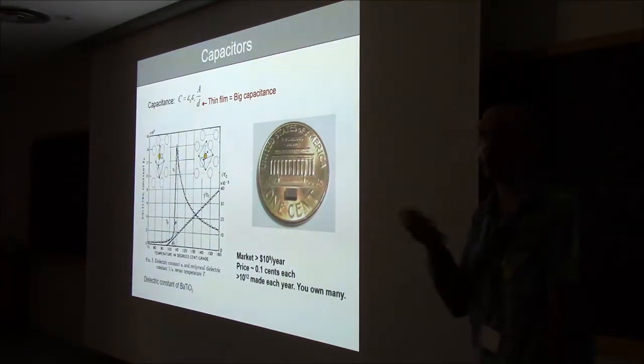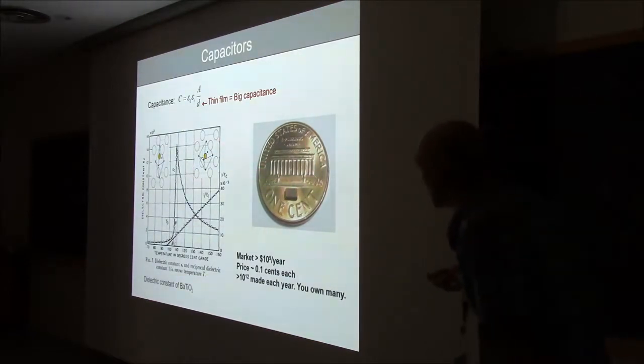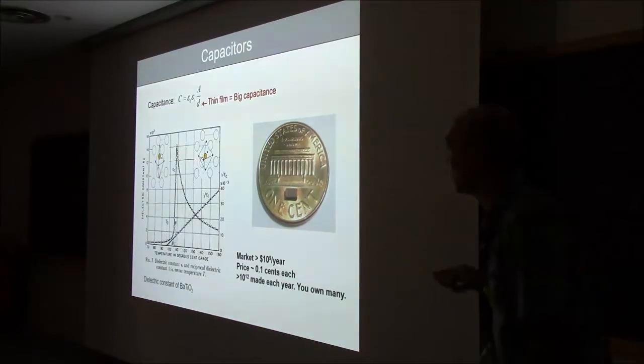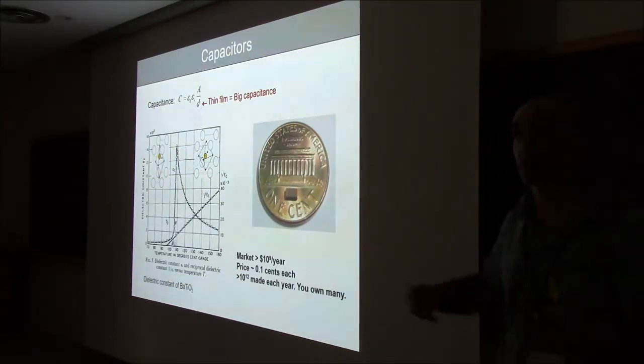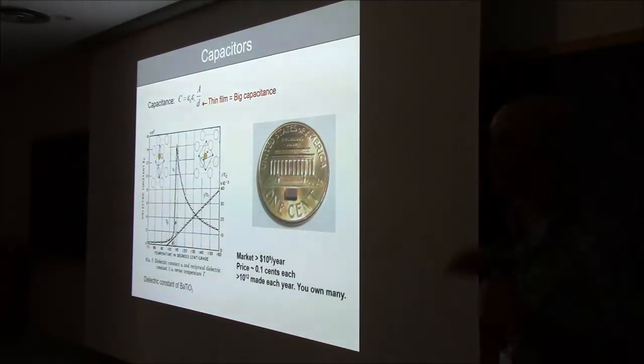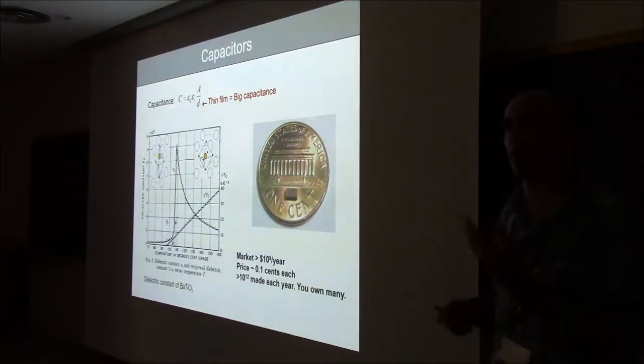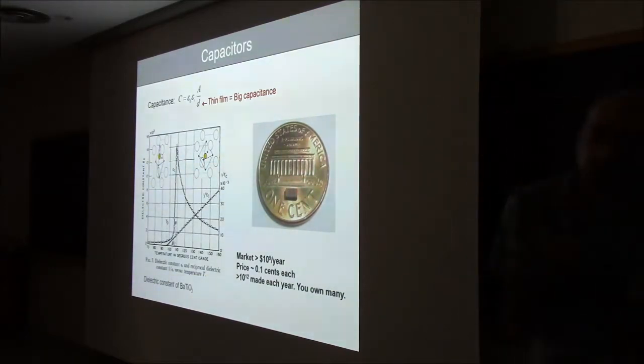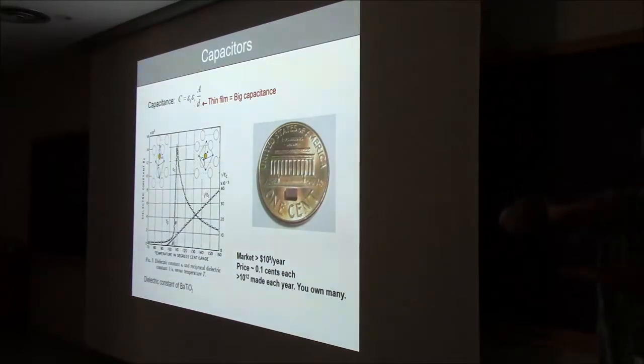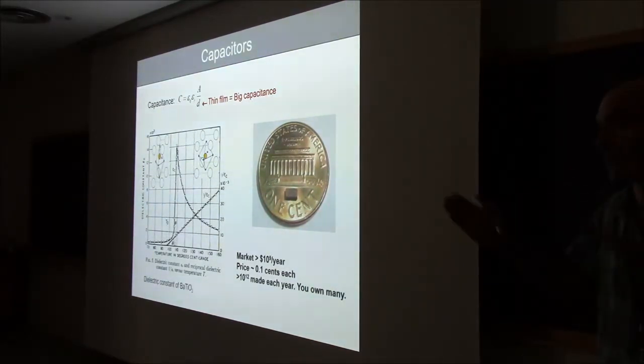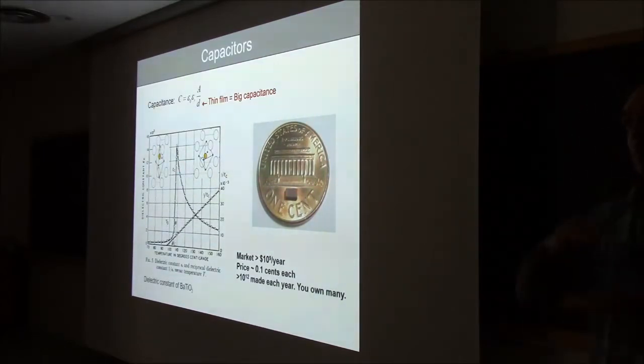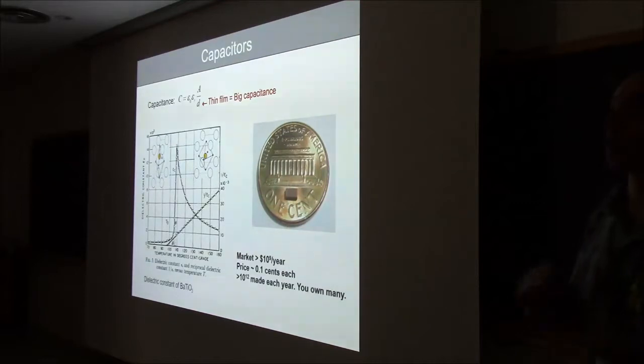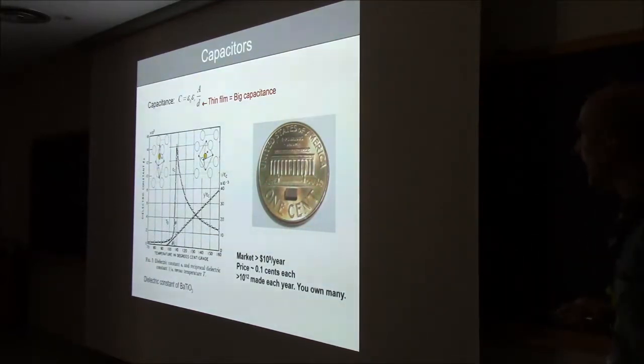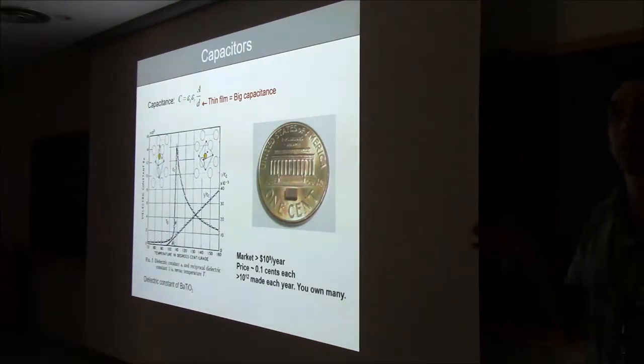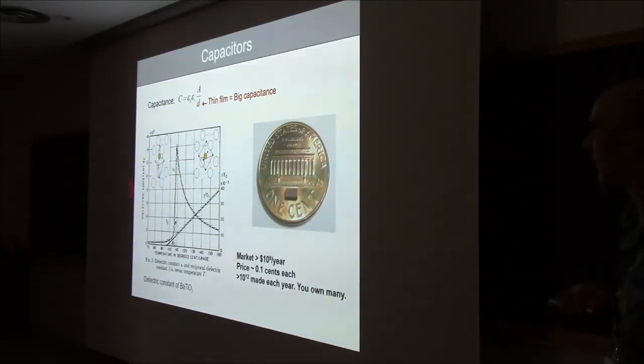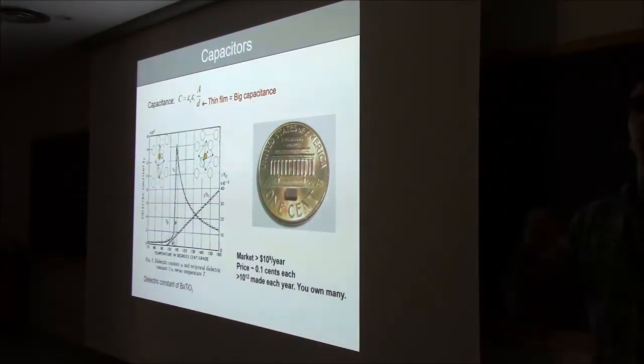You can also use what I've just described, the polarizability of the unit cell. At high temperature it's not polar, at low temperatures it's polar. In between, it doesn't know what it wants to be, so it's extremely susceptible, which means that the dielectric constant is very large, of the order of thousands or even tens of thousands. What this means in practical terms is that if you have a parallel plate capacitor and you put nothing, you measure a capacitance. If you put a ferroelectric with a dielectric constant of 10,000, then you can store 10,000 times more charge, and you can immediately see that this is useful. It's so useful, in fact, that this is by far the biggest application of ferroelectrics. It's not to use its ferroelectricity, it's not to use its polarization, it's to use its polarizability.